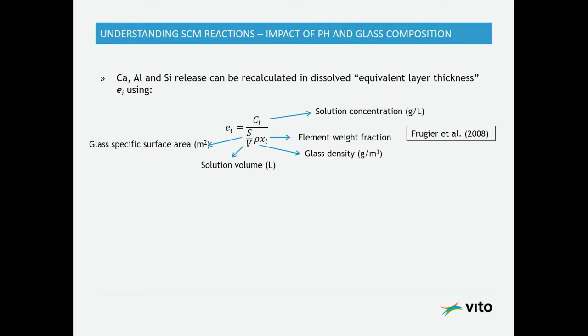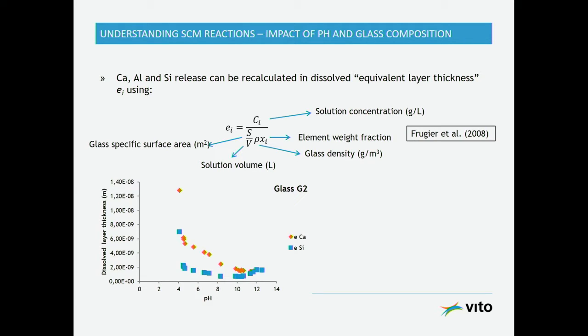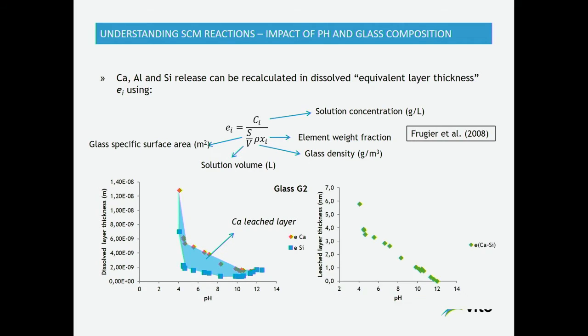One can calculate this from pH, but you can also look at the calcium, aluminum, silicon concentrations in the solution. And based on the difference between how much calcium you release and how much calcium is in the glass, compared to how much silicon you release from the glass, you can also start calculating the leached layer thickness. So if there is a silica-rich layer at the surface of the glass or not. And one can really see that, if you calculate equivalent dissolved layer thicknesses here, they are similar at high pH, but there is really a big difference here at lower pH. So this is really indicative for calcium leached layers established at lower pH, actually of incongruent dissolution at lower pH.